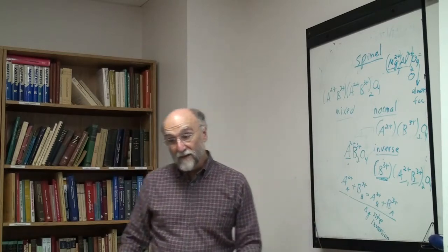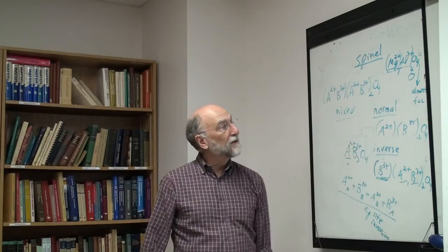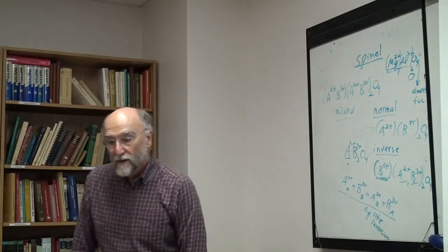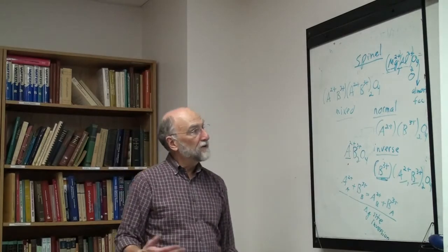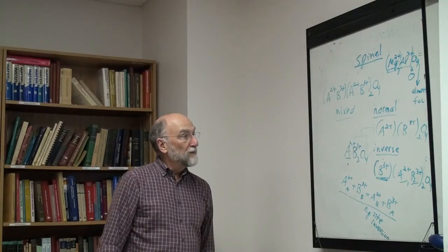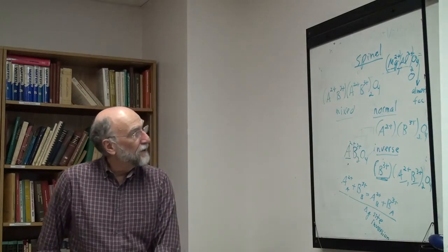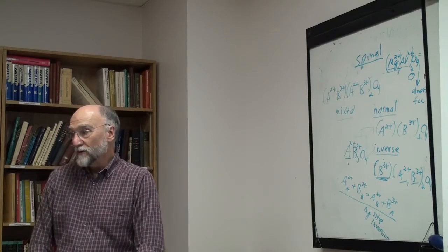Okay, you can also affect the electronic conductivity, because these things are electronic conductors. It works by hopping, and electrons can hop more easily between lattices than among sites on the same lattice, so you're affecting electronic conductivity. By doping these things and playing around with the elements that are in there, you can affect the electronic and magnetic properties and come up with what's called functional ceramics. They're just very ubiquitous compounds that are all over the place.